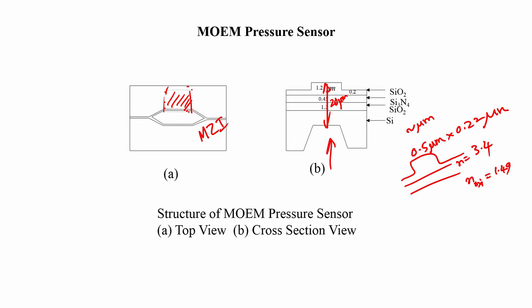silicon photonic devices. This particular structure has multiple layers: a layer of oxide, a layer of nitride, a layer of oxide, and light could be guided in the higher refractive index region. Nitride has a much higher refractive index than oxide, so light could be guided in this region. This patterned structure of the channel waveguide is effectively for confining the mode in this region by effective refractive index. So, when you apply pressure uniformly on the top of this interferometer, the stress-induced refractive index change is larger here. The other arm of the interferometer is not affected much, and there is variation of refractive index in this region alone, in the diaphragm region, in particular on the waveguide region, and so there is a different phase shift.